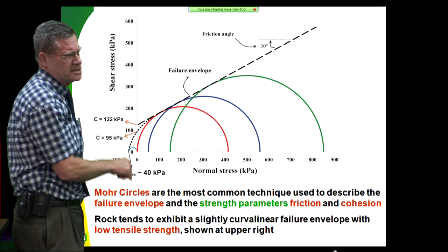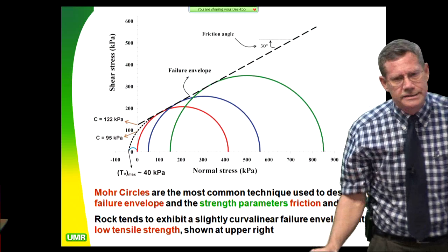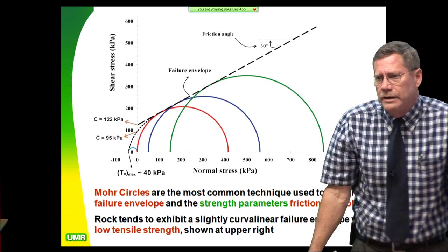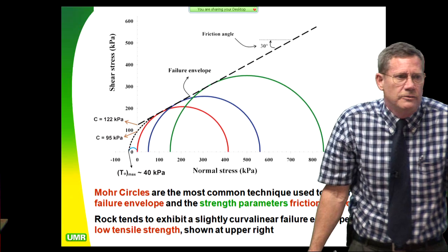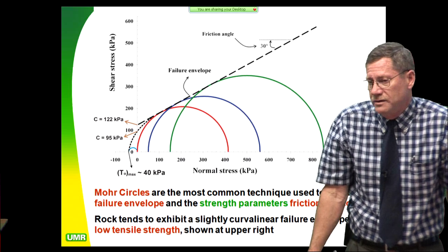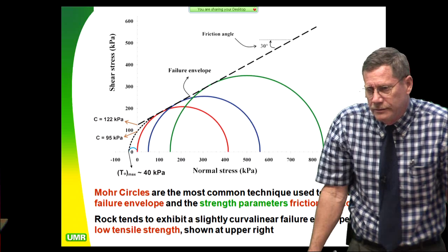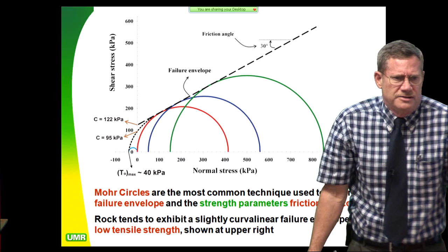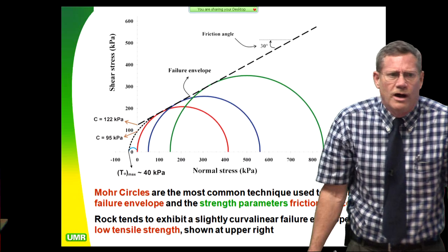Now, if you saturate this and you have anything that's shaley, argillaceous, you're going to see a two-thirds reduction in C. When I get on a dam panel and we're looking at stuff like this, and I give that little speech, my biggest enemy to watch out for is a soil mechanics professor, because they have a religion. It's called the C-phi religion. They're taught that C is an intrinsic property and is not influenced by pore pressure at all. That is bunk. If it was true, we wouldn't get landslides when the pore pressures get higher. Not too many landslides occur when there's no water.